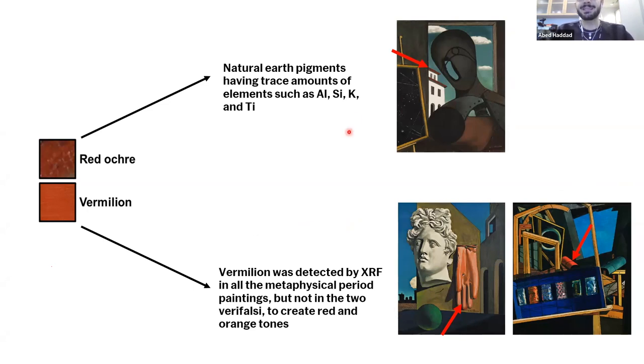But the presence of those in red areas with the absence of other red colorants, like vermilion, for example, identified by the presence of mercury, tells us that there is possibly a use of red ochre. So for example, here in the Astronomer, the red terracotta roofs are done in red ochre. Whereas vermilion is identified across all of the metaphysical works and the Vera Falsi, but not in the two Vera Falsi, to create red and orange tones.